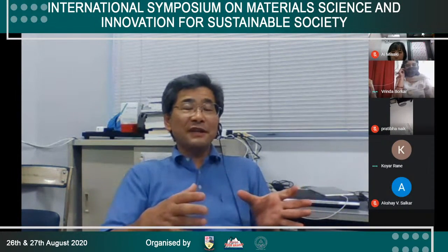Carbon distance is decreased, increased. For the carbon distance increase, it means the nitrogen is going where exactly? But the doping level of the nitrogen is very low. Normally the carbon distance does not change so much, I think. Slightly increasing, I think, because the nitrogen gives the electron to the graphene pi band. So in such a case, the CC distance should be increased a little bit, but the doping level is low, so that does not affect so much, I think.